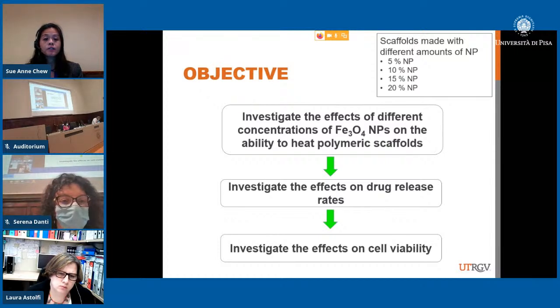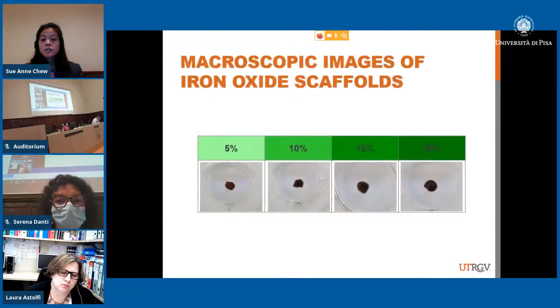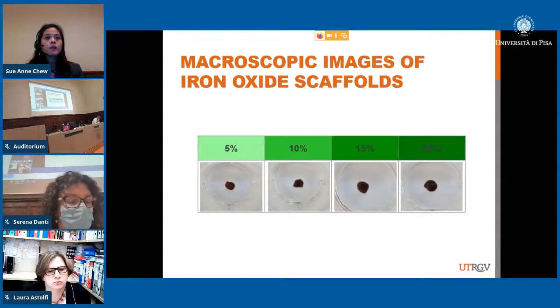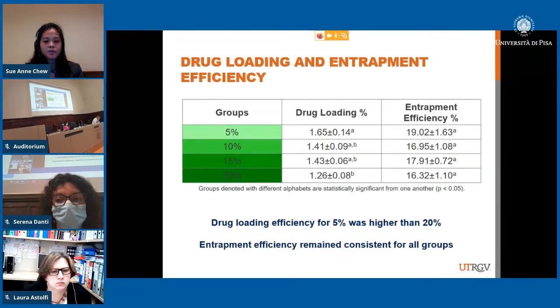So, for this work, our investigation started with looking at the effects of the different concentrations of the iron oxide nanoparticles. And there we wanted to relate it to the effects on drug release rates and then study the effects on cell viability. So this is just some macroscopic images of the scaffold. The iron oxide nanoparticles are very dark, brownish, blackish looking. And as you add more, as expected, we get a darker scaffold. Right now, we're trying to get SEM images. We're having trouble because sometimes the scaffold is still wet or it still has tetraglycol remaining in it. So we have challenges with that. So if you guys have any ideas, do tell me how to look at these scaffolds in SEM.